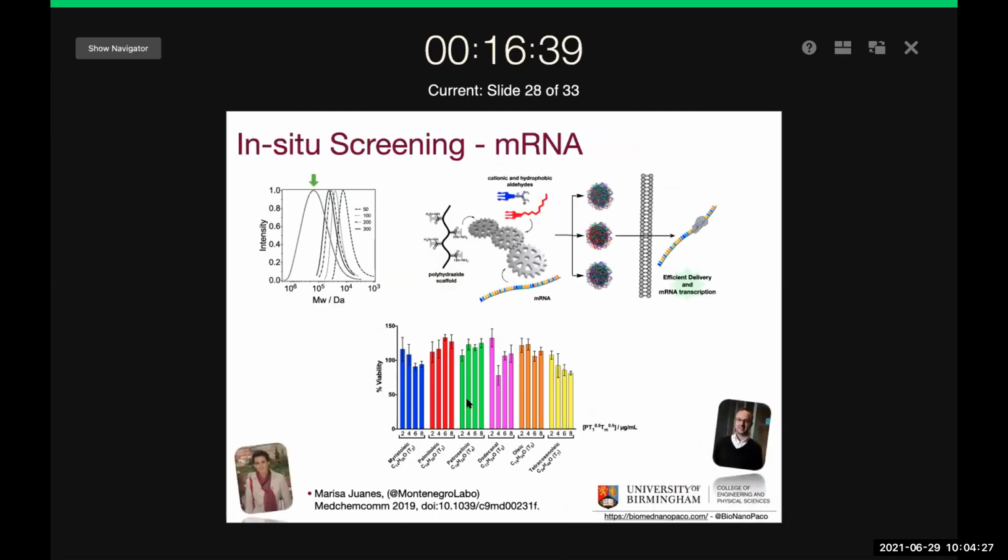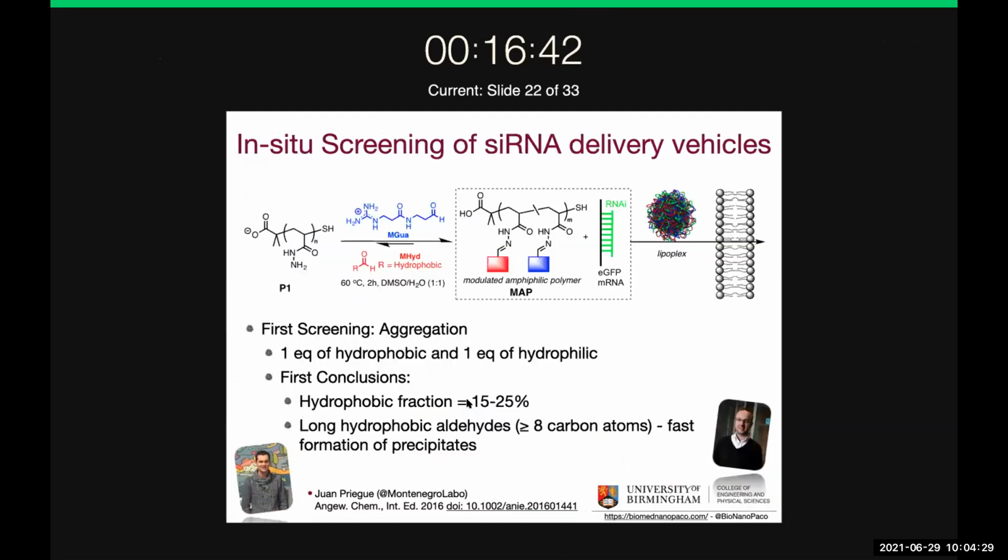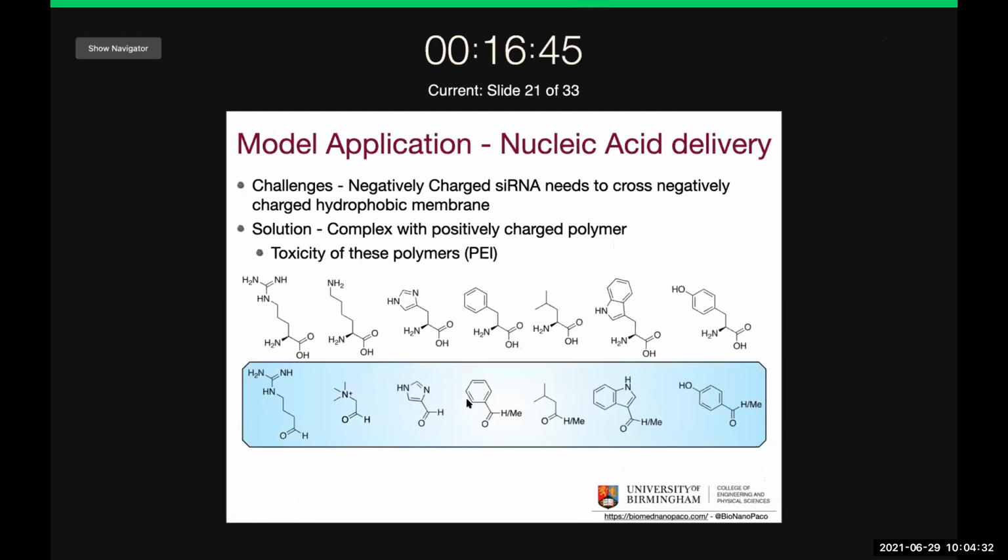So often people will say that what you need, and this is what nature does to make cell-penetrating peptides, which are peptides that go in or through membranes and help, for example, viruses infect, right? If you look at histones, they have a high density of guanidinium groups, which are permanently charged and coordinate to negatively charged RNA. And it's this balance between positive charge, to associate to your negatively charged membrane, and hydrophobicity that allows them to go through the membrane.